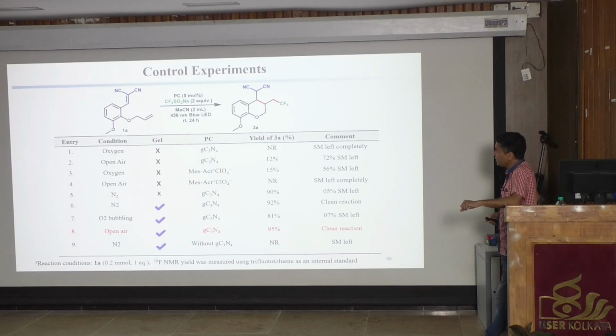CF3SO2Na, 2 equivalents in acetonitrile, and 456 nanometer light at room temperature for 24 hours. So the reaction is happening, this is the cyclization followed by this CF3 installation on this part. When this is in oxygen without gel, there is almost no reaction. In open air, almost no reaction. But in presence of gel, we are getting 95% in open air. That means oxygen cannot permeate through the gel, and the gel acts as a confinement, and we are getting 95%. So a very clean reaction.